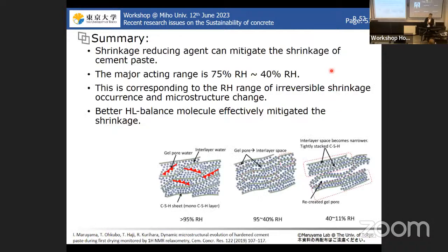Based on some additional measurements, we confirm that the SRA molecules exist in the gel space. So maybe I need to explain something about the CSH structure. It's coming from the proton NMR relaxometry measurement. So we believe that the CSH is composed of CSH sheets, like the Feldman and Sereda model. In the case of the sheets, the distance is very small, and we can define this space as interlayer space. But if the distance between sheets is large enough, we can define this space as gel pores.